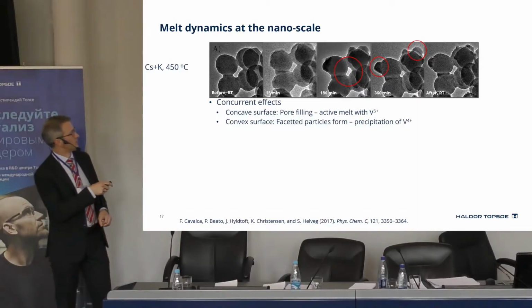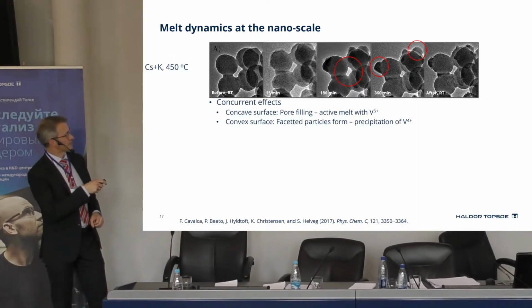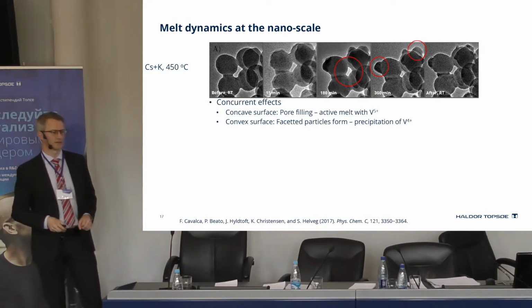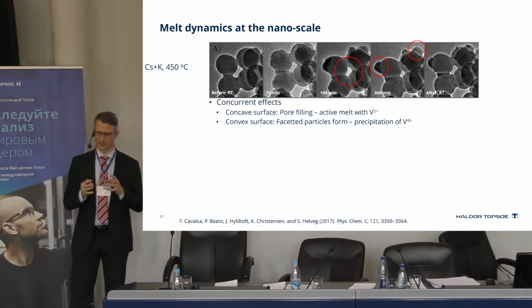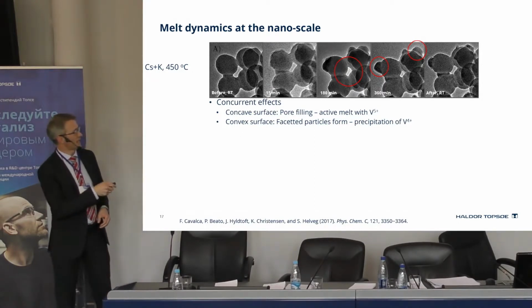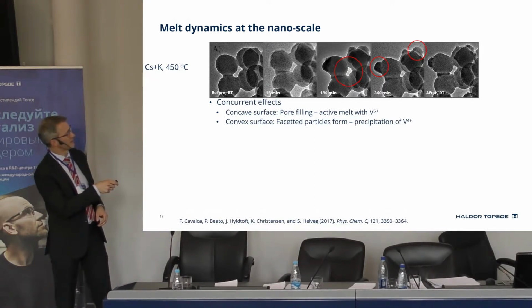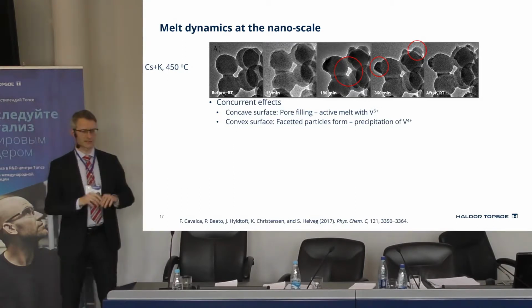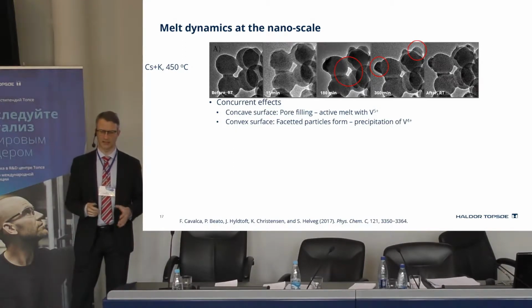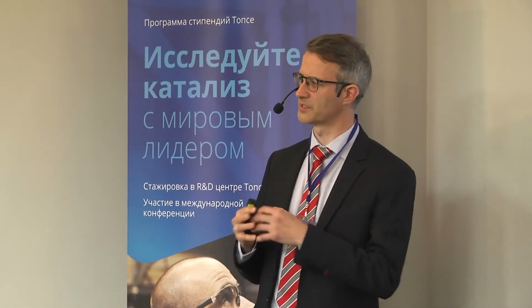So here we believe that what we see here is the active melt, especially the vanadium 5, the liquid melt accumulating in the concave areas. And on the convex areas, we see the faceted particles, and we think they are vanadium 4 species precipitating out.